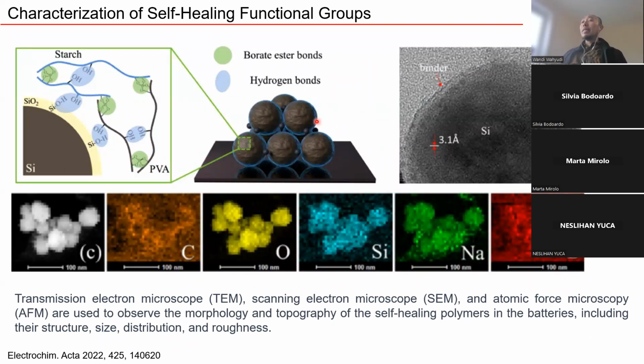There are a lot of techniques that we use to characterize the self-healing functional groups. For example, the authors in this reference use TEM. We also can use SEM, scanning electron microscope, and atomic force microscopy to observe the morphology and topography of the self-healing polymers in the batteries, which includes, we can study also their structure, size, distribution, and roughness level of the electrodes. In this literature, they combine two different types of polymer binders. And by using TEM, they show how is the contact between the silicon particles and binders.